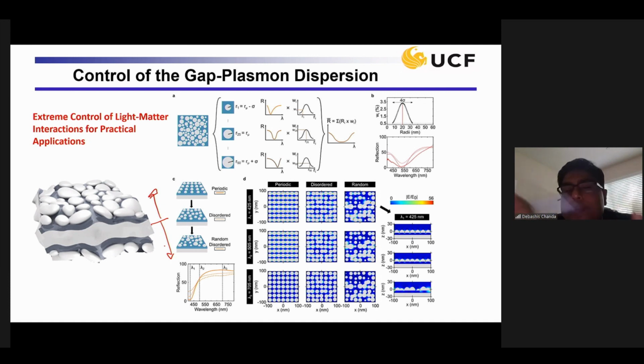And again, we studied optically what happens. We started with the periodic arrangement of nanoparticles, then introduced a little disorder. For the whole structural color field, all this plasmonic metamaterial and photonic crystal, for the last 3-4 decades, we could only do periodic patterns. The problem is that with a periodic pattern, the color is very angle dependent, meaning the color only appears at a certain angle. If you move your head or move the structure, you do not see the color. That was a problem. So we started studying what happens if we introduce some kind of disorder into the structuring of this nanoparticle, from quasi-disorder to complete randomness. And we found that when we achieve a pattern closer to random on this 5-layer architecture, we could create completely angle and polarization independent color, which I will show. That is the whole goal.